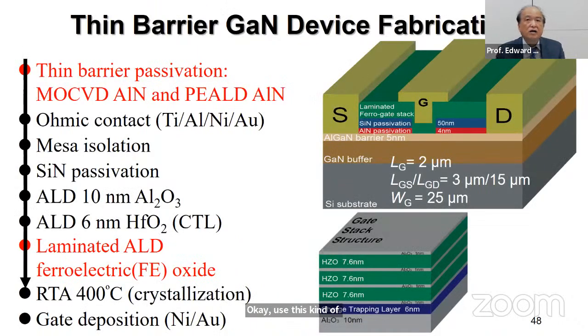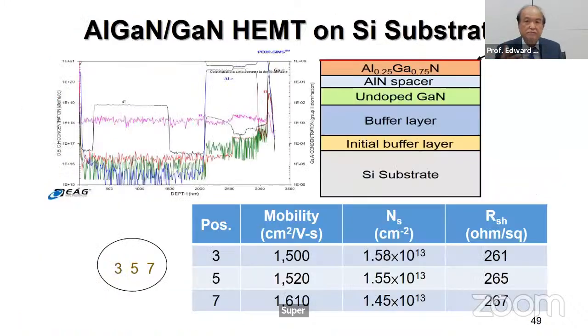And then, this is the thin barrier layer. Using this thin barrier layer, we again construct the whole device with this superlattice, hafnium oxide superlattice. And we can see that the mobility is around 1500 centimeters squared per volt per second, the charge is around 1.5, and the sheet resistance is around 260 ohm per square.